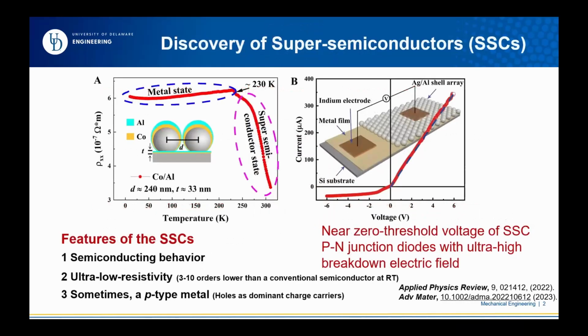First, for these nanomaterials, a little bit of background. We did some nanomaterials patterning. We used polystyrene spheres and made very nice arrays. After that, we deposit very thin layers of metals. Typically it's bilayers. For example, in this one, we deposit cobalt and also aluminum. They are metals, right? And we did this temperature dependence.